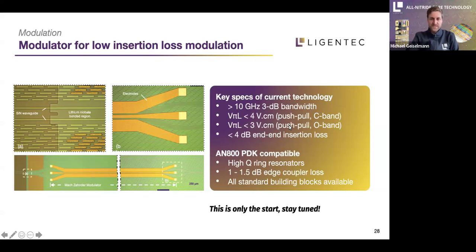in first runs. We have bandwidth that is exceeding 10 gigahertz, 3 dB bandwidth, with VπL reaching down to 3 volt centimeters, depending which wavelength, and end-to-end fiber-to-fiber loss of less than 4 dB, which will be much lower in the future. So this is only the start. So we will get the fiber-to-fiber loss of such a modulator device much lower than this 4 dB. And the big advantage, apart from the very low loss, is the compatibility of the PDK, that we have high Q ring resonators, very low loss edge couplers, and all standard building blocks available in that platform.